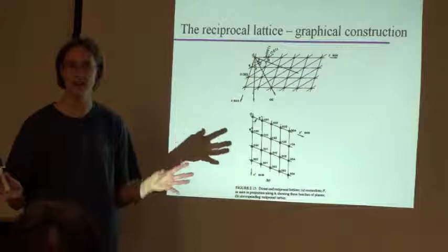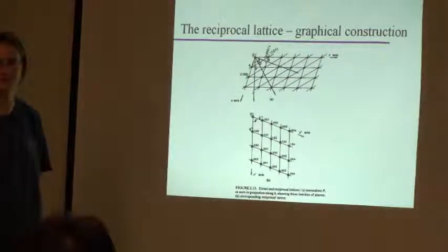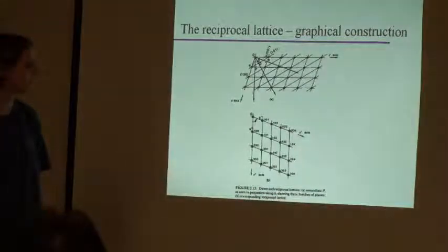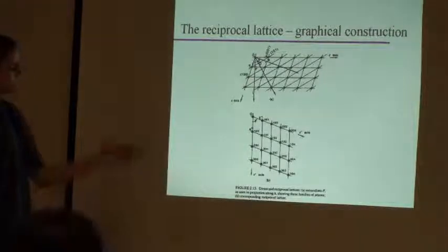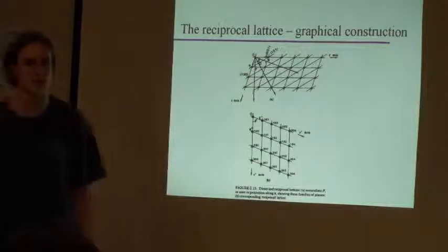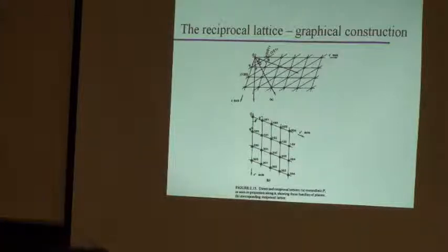So, everything kind of does go back to where it started. And you will get this reciprocal lattice. You'll have an A star and a C star axis in it, okay? Yes? So how do you tell your normal? How do you determine normal? You use a goniometer, something that indicates 90 degrees, and you measure 90 degrees from your lattice plane.